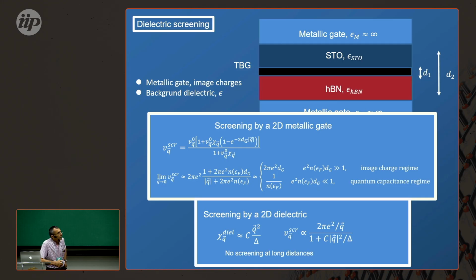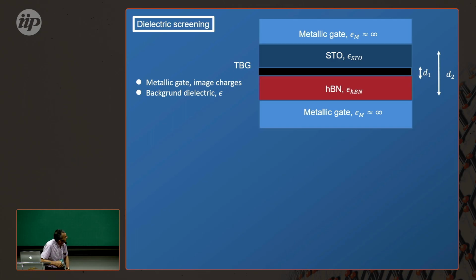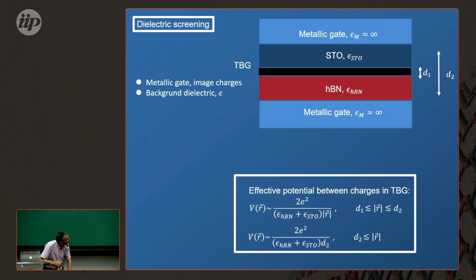At very long distances, the dielectric constant of a two-dimensional dielectric is 1. It doesn't screen at all. So this approximation we theorists have been using all the time, I think it's worth revisiting. So this is the kind of crossover one can expect as a function of the distance between charges in your twisted bilayer.